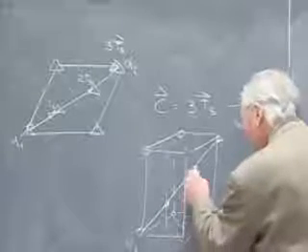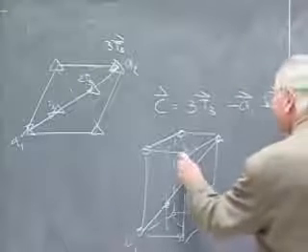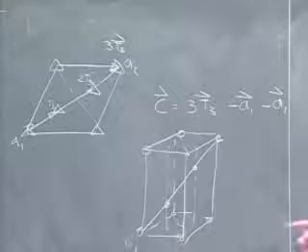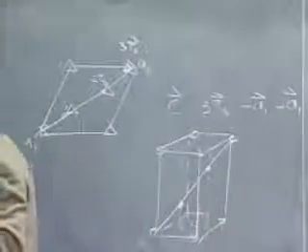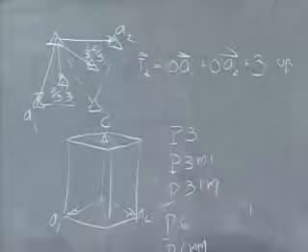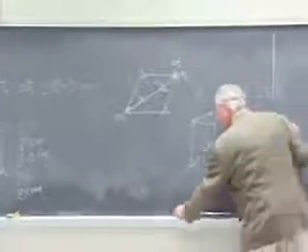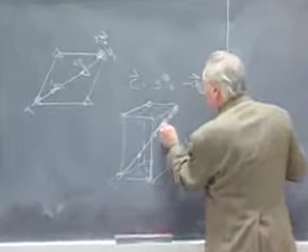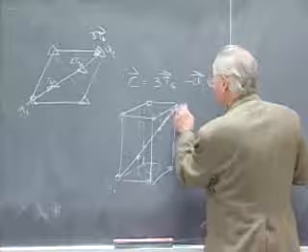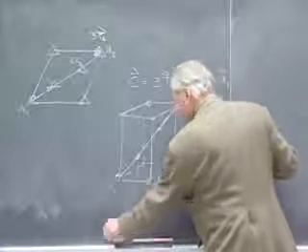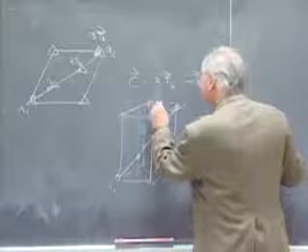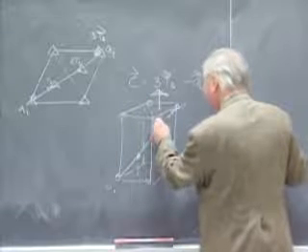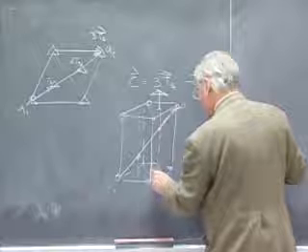This double body-centered cell, so to speak, actually can be redefined in terms of a primitive cell, not a primitive cell that is this particular description of a primitive hexagonal lattice. This is not a primitive hexagonal lattice. But suppose I go from this interior lattice point along the long diagonal of the cell to this location and call that A1. Remember that there is a threefold axis snaking down through the center of this triangle, goes through the lattice point and comes out the center of the triangle below.